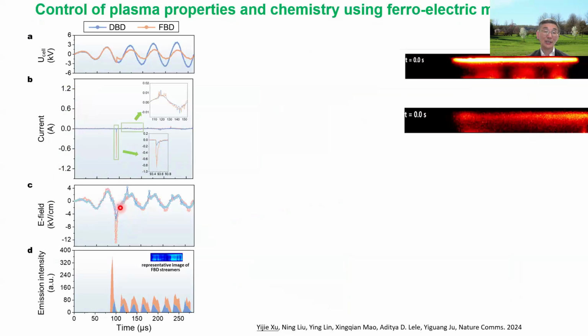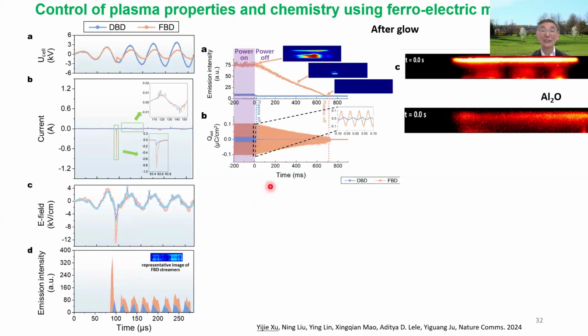And the yellow one, again, is ferroelectric materials, called ferroelectric barrier discharge. At the breakdown point, the electric field is doubled because the polarization timescale of ferroelectric materials is even shorter than the plasma breakdown. So plasma has another response when the charge is generated, and then you generate enormous surface charge that increases that electric field and increases the emission from plasma.